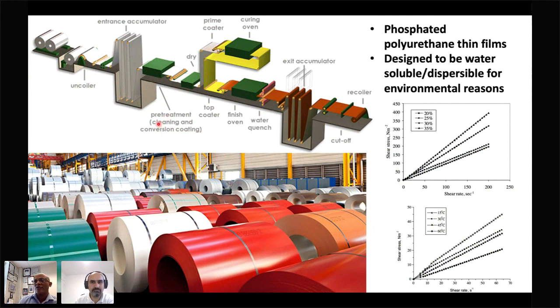The phosphate conversion coating results in a non-conductive layer of metal phosphate, in a crystalline form, and that crystalline metal phosphate is non-conductive, and therefore it prevents the metal from corrosion. So that's really the idea. But this process is rapid at the beginning, but kinetically it becomes very, very slow towards the end. So it never really goes to completion. And so that was the challenge that we had.